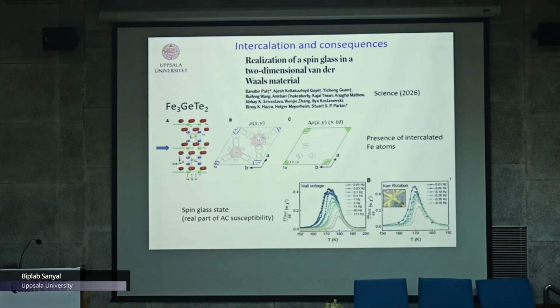Very interesting, but the story doesn't finish here, because they claim that they see some spin glass behavior if you have iron atoms in the van der Waals gaps. The microscopic picture is not known, but the experimental observations show a frequency dependent shift of the AC susceptibility, and from there they say that this is a realization of a two-dimensional spin glass phase in this kind of van der Waals magnets, which is very interesting, and a lot of things have to be understood here. Nevertheless, my system is similar to this.